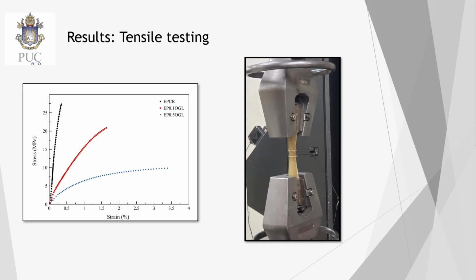In the sample which has 0.5 of graphene, the behavior is completely different. The material is found in a transition state between brittle and ductile, with great increase in elongation, up to 3%, and great decrease in fracture strength, of about 64%. So apparently, the addition of 0.5% in weight of graphene led to a more flexible material.